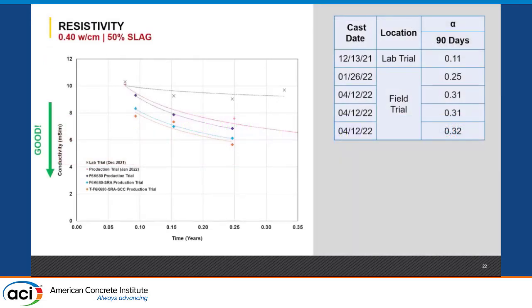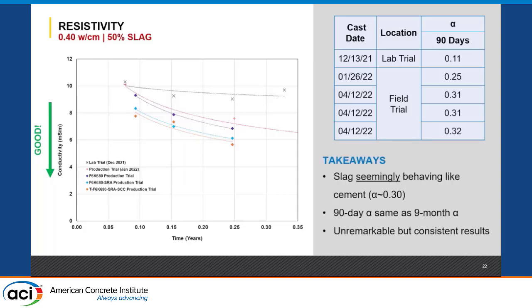And right away, we know that with the slag, the resistivity was just awful. These lines are super flat by mathematical standards, which are giving me these just god-awful alphas. I mean, you remember I was talking about 0.3 to 0.6. I started with 0.11, and I barely got to 0.3. So this is behaving like an OPC, seemingly behaving like an OPC. And I also found that 90 days was about the same as 9 months, so it was not a time issue. And at the time, these were, what I'm going to say, unremarkable, but good enough numbers because the service life model worked. So I didn't like them, but it was good enough, so we moved on.